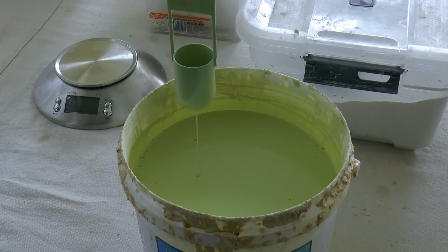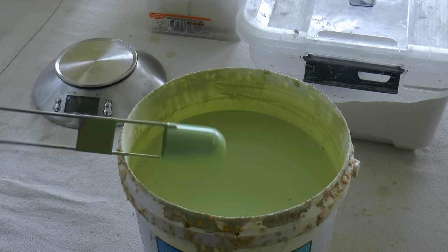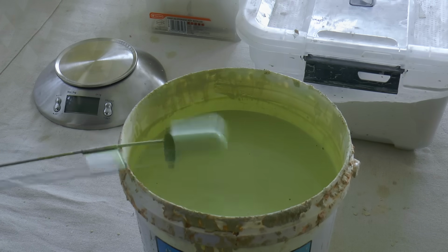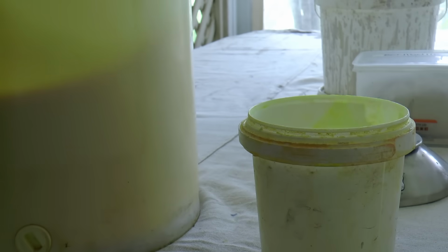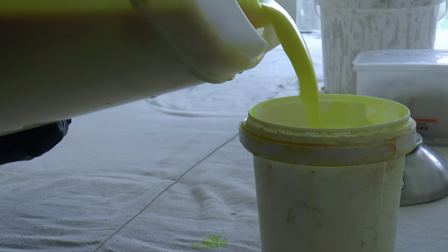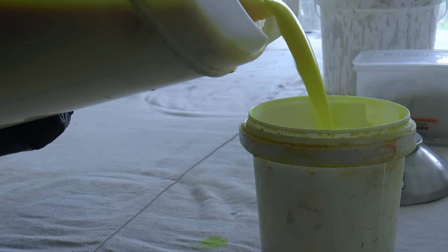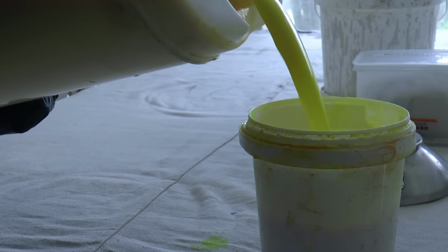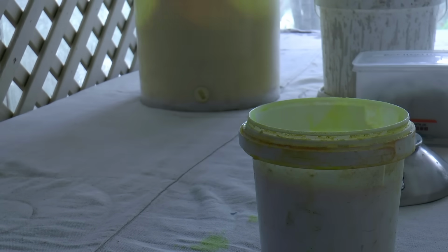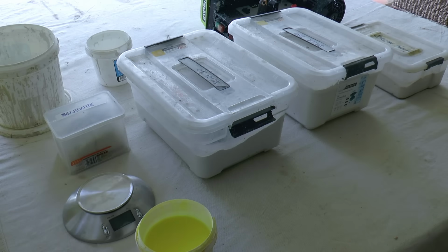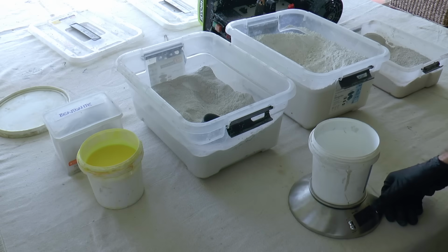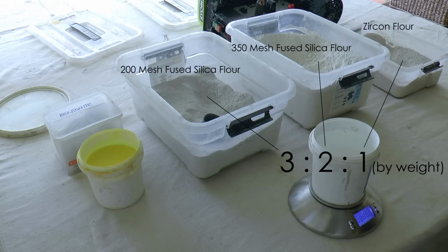It consists of a colloidal silica binder into which is suspended refractory flour until a desired viscosity is achieved. In its raw state, the colloidal silica has some defoaming and wetting agents, as well as the drying indicator that gives it that vivid colour. But it pours much like water. So the first step is to prepare the flour that'll transform it into a more useful viscous mix.